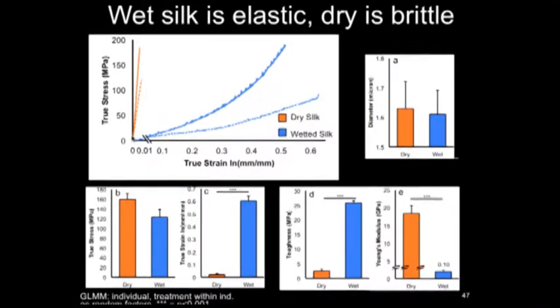So what we found when tensile tested at different conditions is that the mechanical behavior is very different. Dry silk becomes very stiff and not very stretchy, much like what I showed you with Kevlar, except it's not nearly as strong. However, when wetted, not only do they become much stretchier, they don't lose very much of their strength, and they become very compliant, meaning that we can stretch them and then return them back to their original starting position without much loss in properties, without overstretching them. If we were to stretch up to 20–30%, we could return them back to their original starting point and be able to stretch them again. Similar to how we might expect them to perform in nature, where we would potentially need to stretch and unstretch a struggling prey that would be caught in the webs.